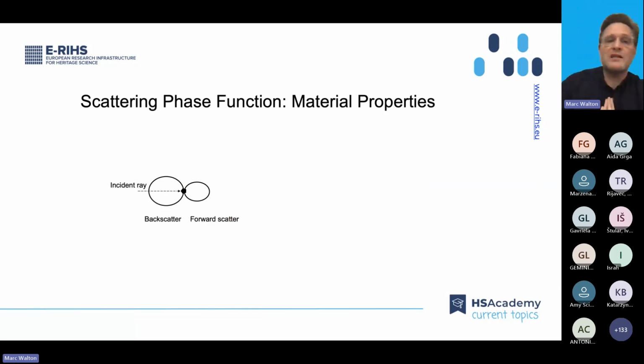From my perspective, as someone who has worked very heavily in material science, you can also tie the BRDF back to its material properties. And I'm showing you here a diagram of what we would typically try to think about when we are talking about material properties from this point of view of light coming in and interacting with, say, a particle, what is called the scattering phase function. So you can imagine some sort of incident ray coming in, hitting a particle. Part of that light is going to be back scattered toward the viewer. Some of that is going to be forward scattered through other elements that are in some sort of painted structure.